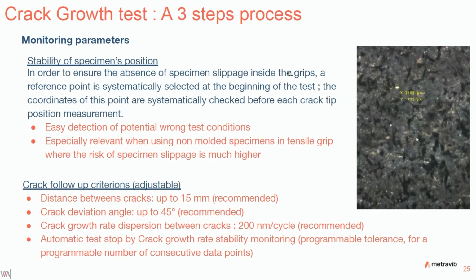So what about the monitoring parameters? First of all, the stability of specimen position. In order to detect any specimen slippage inside the grips, which could happen, a reference point is systematically selected at the beginning of the test. You have an example in this picture, and the coordinates of this point are systematically checked before each crack tip position measurement. This is an easy detection of potential wrong test conditions, and it is especially relevant when using non-molded specimen in tensile grips, where the risk of specimen slippage is much higher.